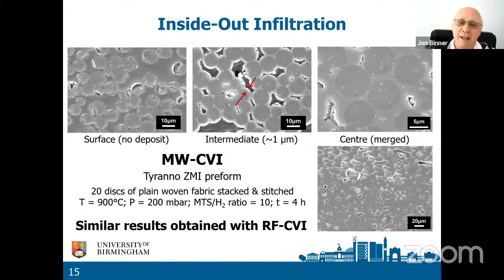And at an intermediate distance between the surface and the center, you've got a deposition of about a micron or 2 microns. So you can see that this is clear evidence that the inverse temperature profile really exists, and you get exactly the same results with RF CVI with carbon fiber-based composites. So this enables us to cook from the inside out. We can avoid all those machining stages, and we get much faster processing.